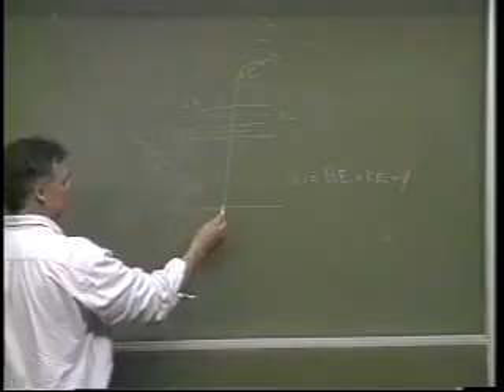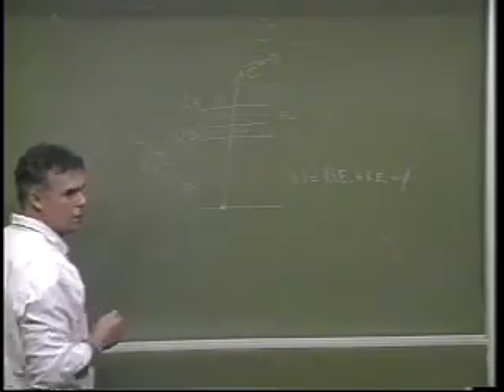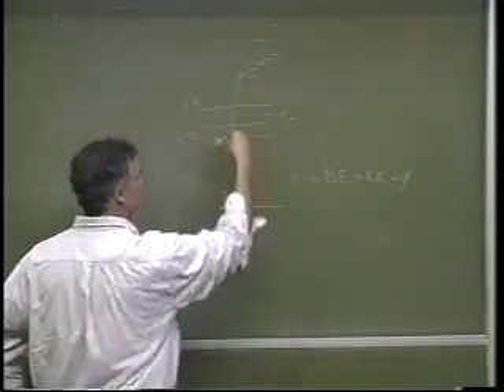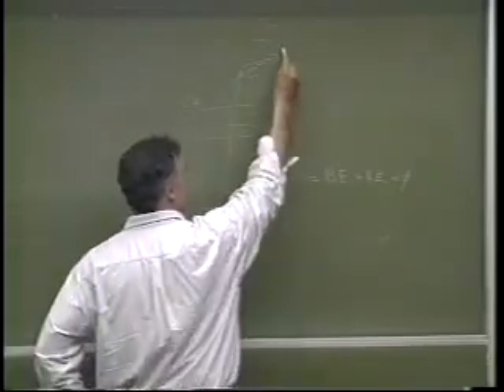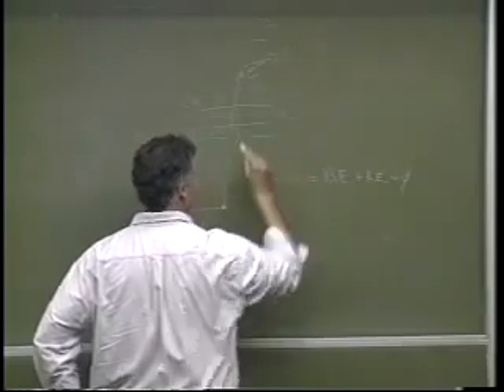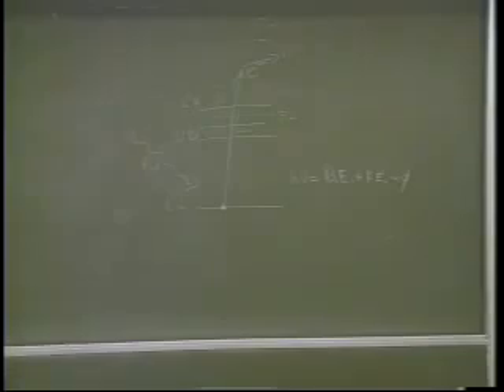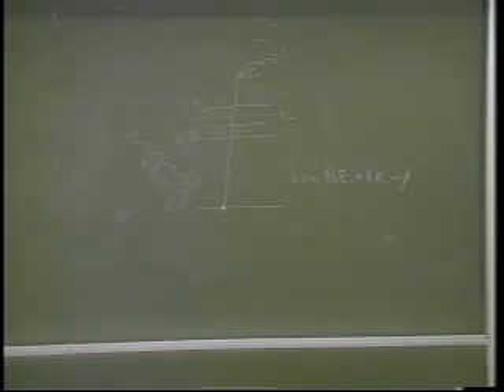So in this case, we're measuring the filled states, the ones that have the electrons in. We bring in an X-ray, kick out the electron. You can measure the kinetic energy of the ejected electron and determine what the binding energy levels are. Now, I'm not sure what your question was here. The question is, during the lecture, you said that there's two ways to get X-ray absorption. One is detecting the transmission. The other way is detecting the photoelectron. Okay, I see where the question is. I'm questioning why the number of the photoelectrons is proportional to the absorption. Okay, I see. All right, so photoemission process.